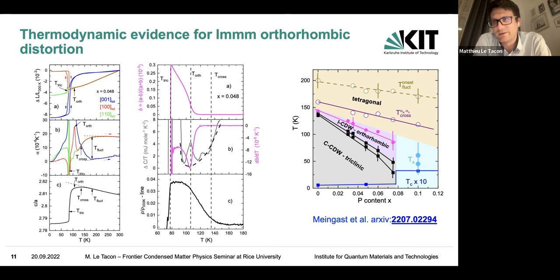You don't have a very strong enhancement of the electron-phonon coupling. You don't have a peak in the joint density of states at that Q, for instance, a good nesting, if you like. So from a conventional CDW-like picture, it doesn't seem to be the case, but I still haven't really figured out what it is that forms this CDW. We call it a CDW, but there's a good chance that it is a bit of a different object.